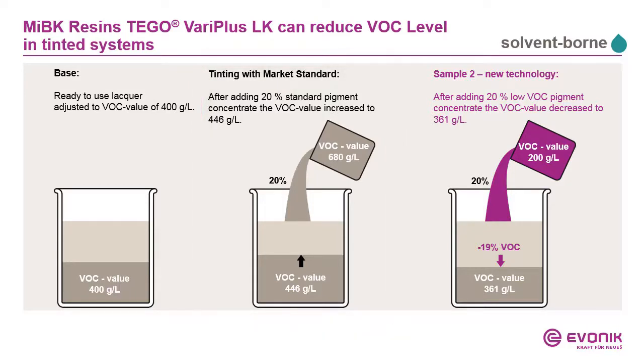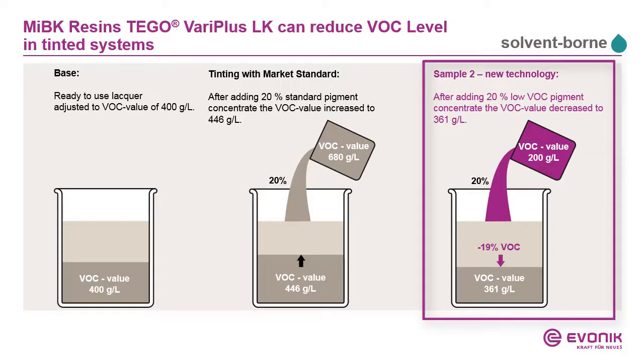Now sample 2 means we use a low VOC colorant. And with the low VOC colorant with organic pigments, we can go down to 200 grams per liter of VOC with the LK. Now we do the same tinting, 20% of this colorant to the base, and we end up with a VOC level of 361 grams per liter. So minus 19% of VOC. So you can use these 19% of VOC, for instance, to adjust the spray viscosity or other things. So you really save VOC when you use a low VOC colorant.